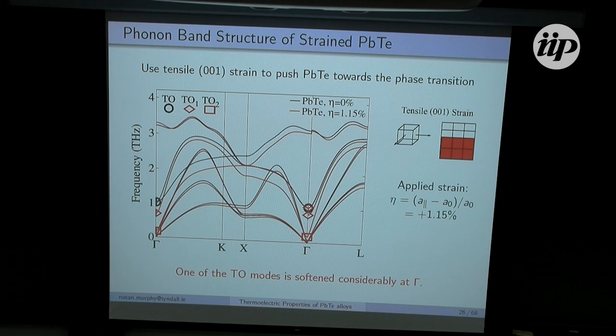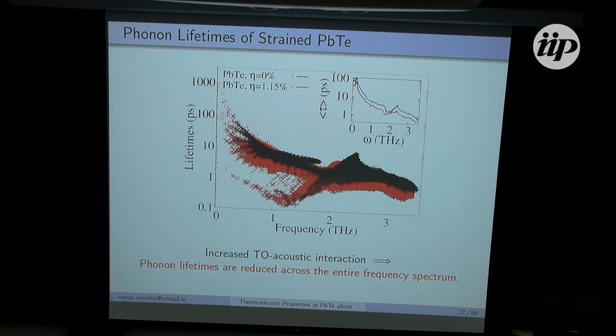So getting back to that, we've softened the TO mode considerably at the gamma point. We've increased that TO acoustic interaction. If we take a look at what happens to the phonon lifetimes, I have here lifetimes due to 3 phonon interactions, and lead telluride again is in black, and strained lead telluride is in red. And we see we get quite a substantial reduction to the phonon lifetimes due to this increased TO acoustic interaction.